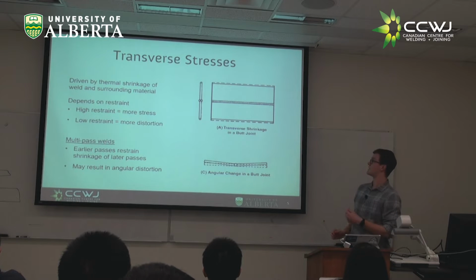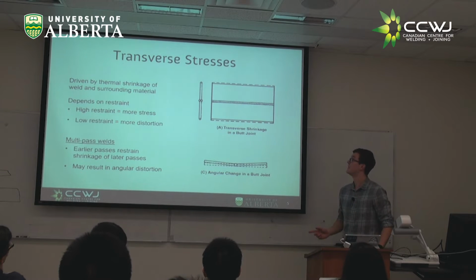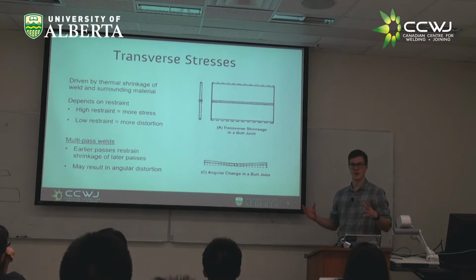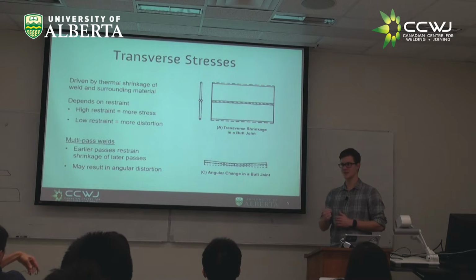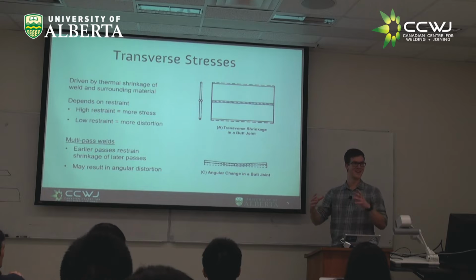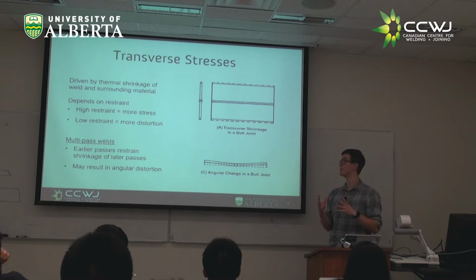So I mentioned this a little bit on the board, but I'll go through it here. Transverse stresses are driven by the thermal shrinkage of your weld. One of the misconceptions about transverse stresses is that it's just the weld metal shrinking. You have hot weld metal, it's like you poured that hot weld metal in there, it cools off, and it shrinks. In reality, that's not nearly enough to account for the thermal stresses and the thermal shrinkage you see in the transverse direction. What happens is if you have something restrained and you heat it, those plates are actually going to get bigger as you heat them.